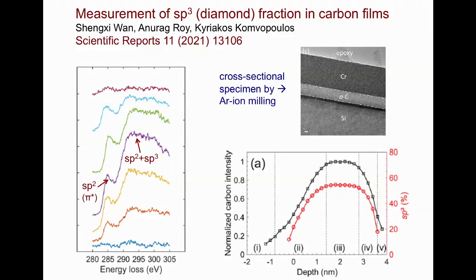EELS can measure the ratio between these two kinds of bond because carbon K-shell ionization edges, seen here on the left, exhibit a sharp pi-star peak when sp2 bonding is present. By quantifying the ratio between that peak and the subsequent broad peak, the fraction of diamond-like sp3 bonding is here plotted against distance through the carbon layer as the red curve on the right-hand side.